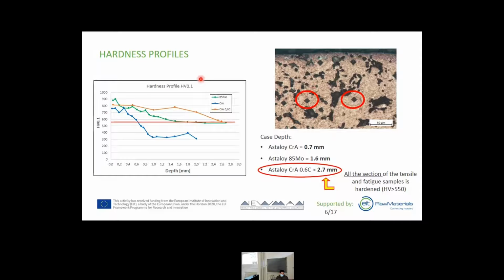After carburizing, quench and tempering, we performed the hardness profile to evaluate the case depth of the three powders. In this image, we can see that the Astalloy CRA in blue color shows a case depth of about 0.7 millimeters, while the 85MO and the CRA with 0.6% of carbon show a case depth of 1.6 and 2.7 millimeters respectively. And looking at the case depth of the last powder, we can say that the whole section of the tensile and the fatigue samples is hardened.